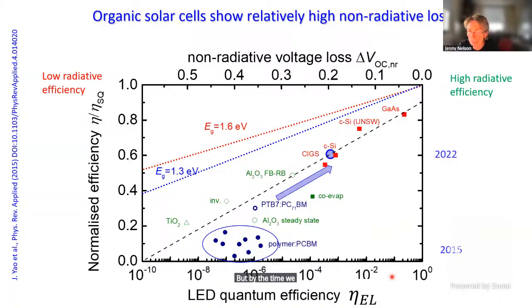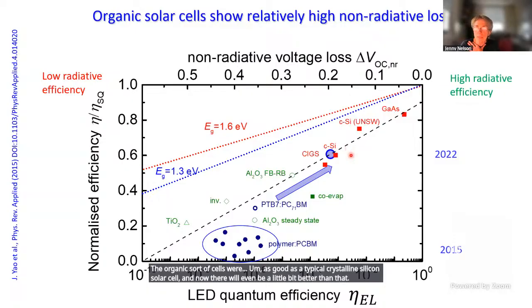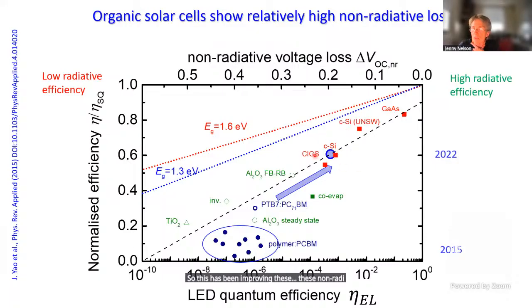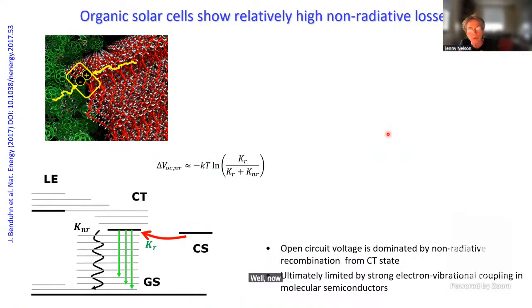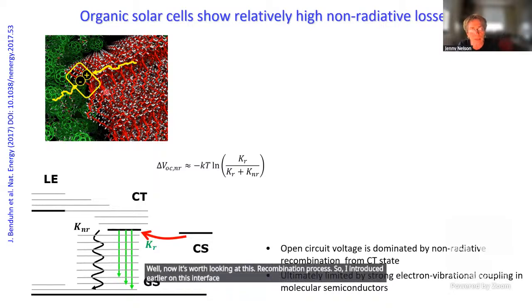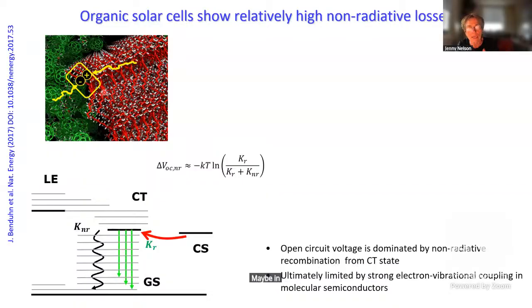But by the time we reached over 19%, which was a couple of years ago, that had greatly improved. And in terms of their thermodynamic losses, the organic solar cells were as good as a typical crystalline silicon solar cell, and now they will even be a little bit better than that. So this has been improving these non-radiative losses. However, they're still not competitive with gallium arsenide, and they're still not competitive with the best perovskite solar cells. So what could be the reason for that? Well, now it's worth looking at this recombination process. So I introduced earlier on this interface where charge separation happens. We absorb a photon, maybe in the polymer, and then you have a charge transfer, and you generate this charge transfer state, which then separates, and the electron and hole go off to the external circuit.